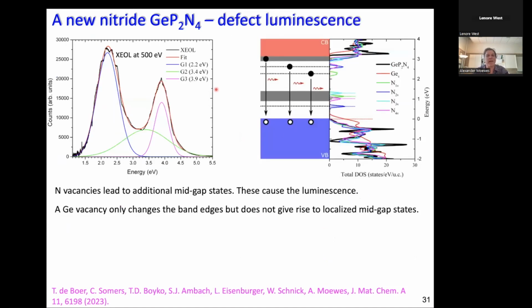To our surprise, we always do that because TEAC implemented a nifty optical spectrometer, we can measure also what's called X-ray excited optical luminescence. So we excite now with 500 electron volt soft X-rays, making sure that we are above the nitrogen edge to efficiently deposit energy. And then we see this black spectrum, the emission. It's called luminescence because it's in the visible. And we didn't expect that, and according to our theory, in quotation marks, it couldn't be present.